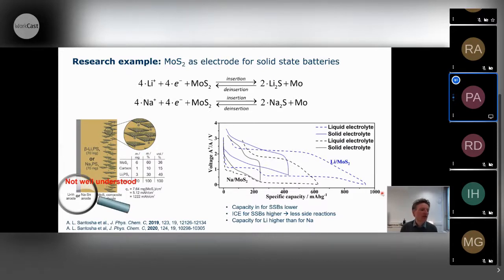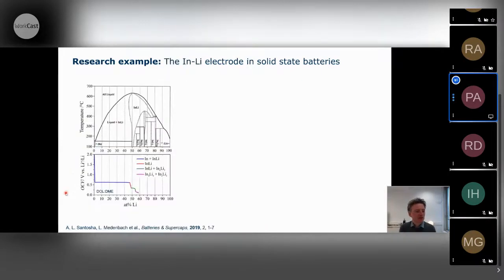All right, so the last example I want to show you is we go to the anode side of a solid-state battery. So we look now at the molybdenum sulfide electrode. In this case, this is really the cathode. These were the solid electrolytes that we used, so LPS or NPS. And what we used on the anode side was a lithium-indium alloy or a sodium-tin alloy, depending on what cell we look at. The lithium-indium electrode is something we had a closer look at because many people use it, but the behavior of lithium-indium as an anode material is not really well understood. And this is a study we also published recently in Batteries and Supercaps.